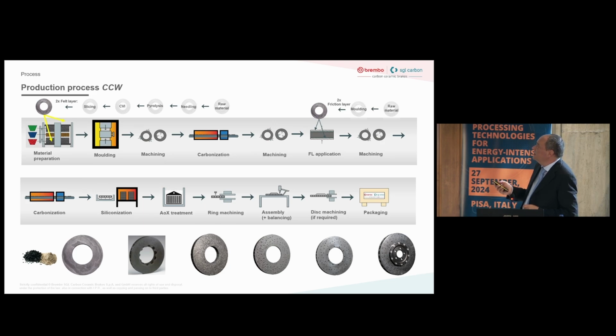The next generation is CCW. So this is the part that we had. It is the production of a carbon-carbon preform that we join by molding with the ribs to produce the ventilation. So this is joined by molding. This is an extra step that we have to produce to have a better material on the surface. Long fibers mean higher strength, but also due to the process here, also better thermal conductivity. So we increase the strength, we increase the thermal conductivity. At the end, we increase the properties of the material. We increase the cost. I left you the answer.